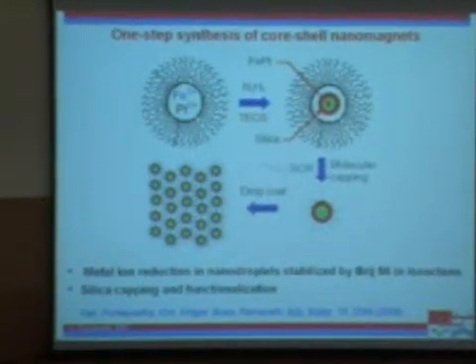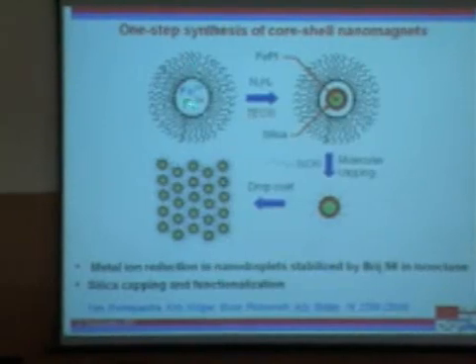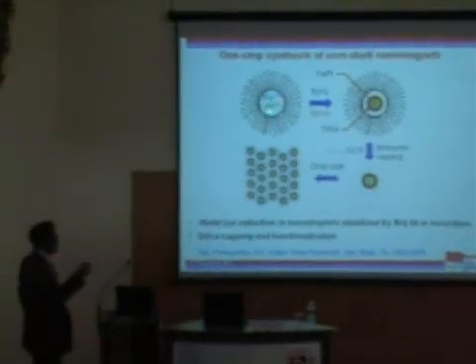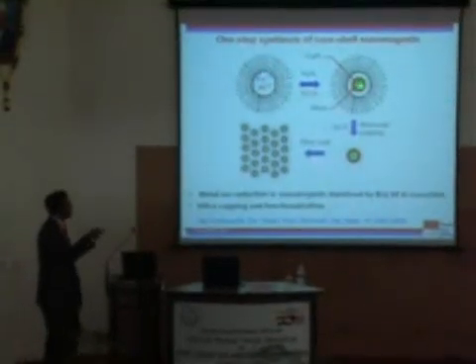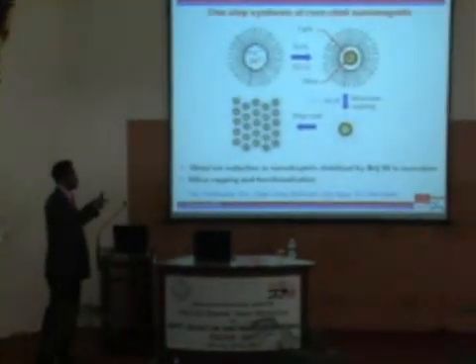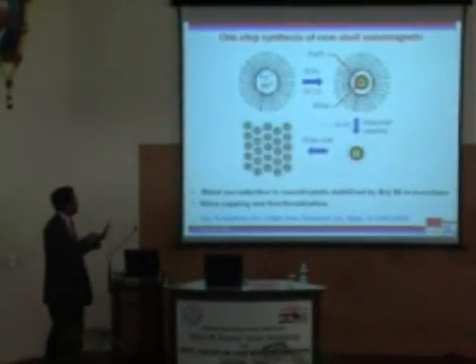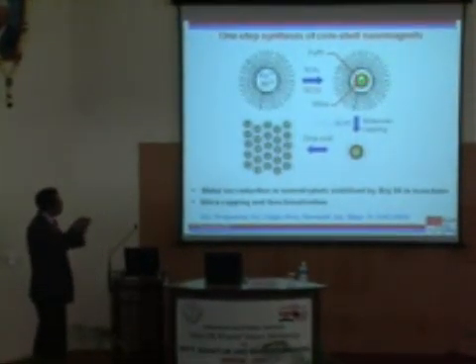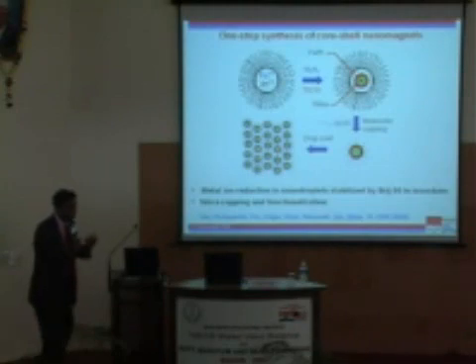What we do is we use droplets of water. Nano droplets of water. These are microemulsions for those of you who know chemistry. Basically, we reduce iron and platinum in this confined environment, to make the nanoparticle iron and platinum. These are still superparamagnetic, so these are not high coercivity. But the one additional thing that we do is we coat it with a very thin shell of silica, so that if I want, I can heat this composite up and I'll be able to change the crystal structure inside, but I will still be able to preserve the overall shape of the particle. That is the overall idea.